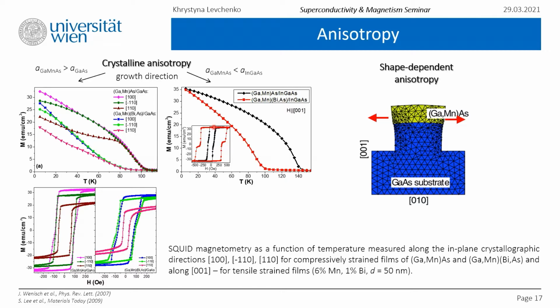into our hysteresis, which is less visible in the case of the ternary, indicated by black, but is way more visible for the quaternary compound, which means that there is probably, in addition to this 001, or perpendicular to the surface, easy axis, some additional axis arising.